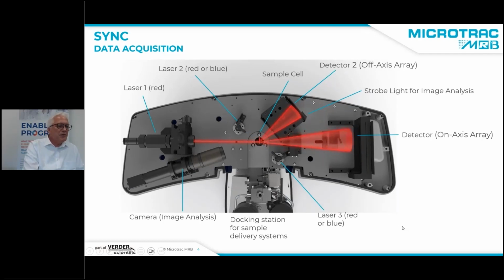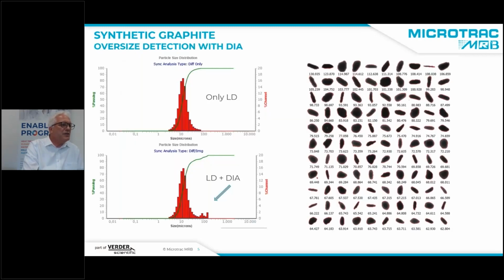The example where we use this for battery materials is shown here. It is a synthetic graphite. What you see in the first picture is the particle size measurement only with laser diffraction. But there are certain oversize particles. The laser diffraction gives us a value of about 10 microns, but there are particles of 130, 60. All these particles are shown here. Statistically, you will not be able to measure these with laser diffraction, but in image analysis, we can follow these.